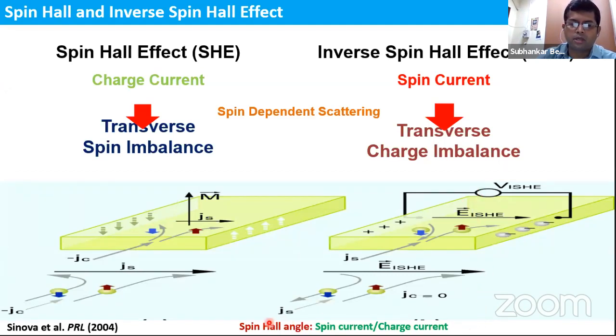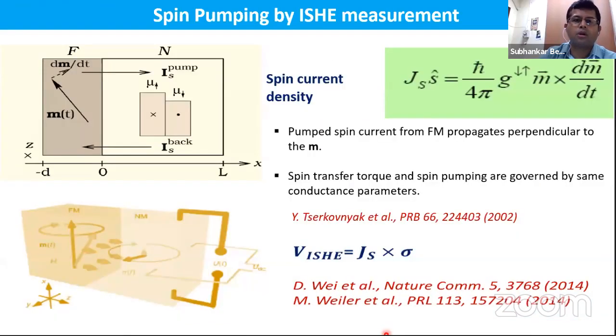A very important parameter is the spin Hall angle, which is really important from the application point of view. It's the ratio of spin current to charge current. That means how efficiently you can convert between charge and spin. And spin pumping is an interesting phenomenon when you have a ferromagnet and a non-magnetic substance. It can be a heavy metal, an antiferromagnet having spin orbit coupling, a topological insulator, a chalcogenide, or any other material which can exhibit high spin orbit coupling. People have even shown it can be another ferromagnet, and then also you can get spin pumping. So basically, you excite the spins in the ferromagnet using ferromagnetic resonance, and then you pump the spins from the ferromagnet to the non-magnetic side.